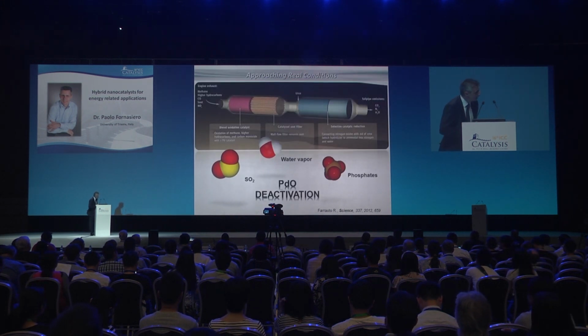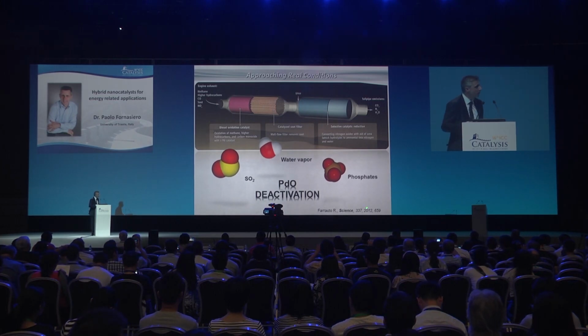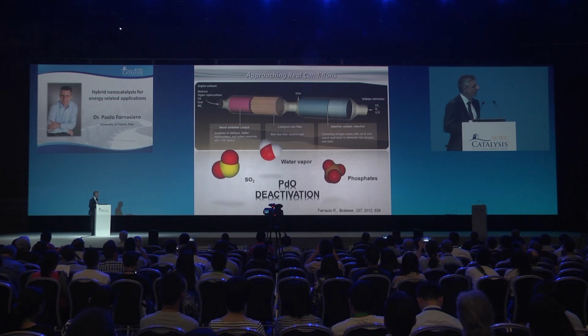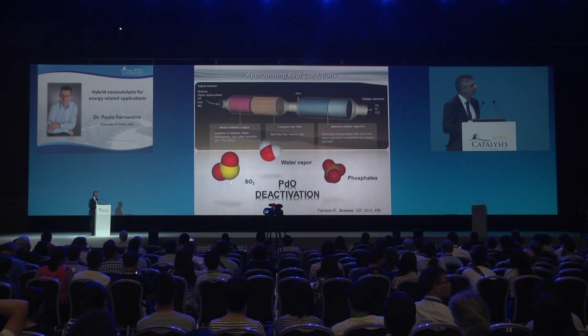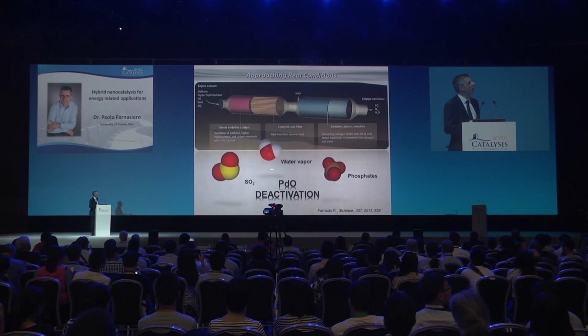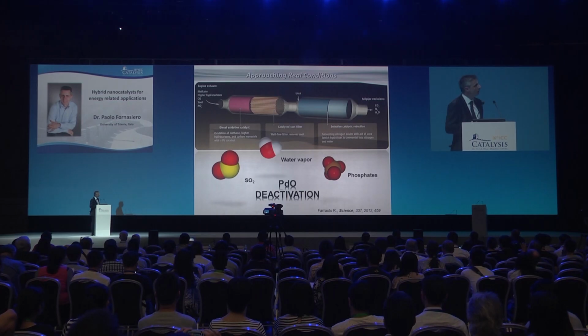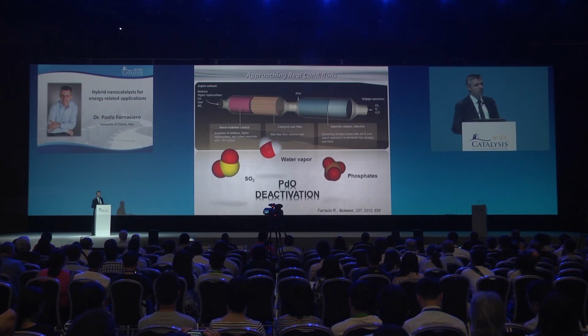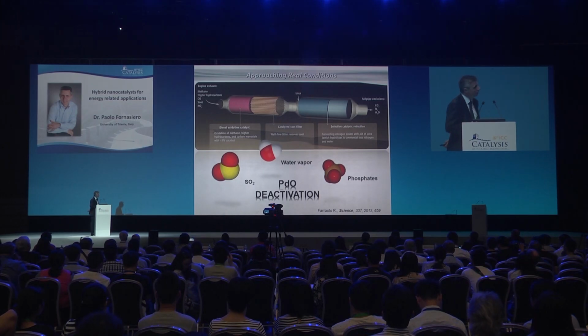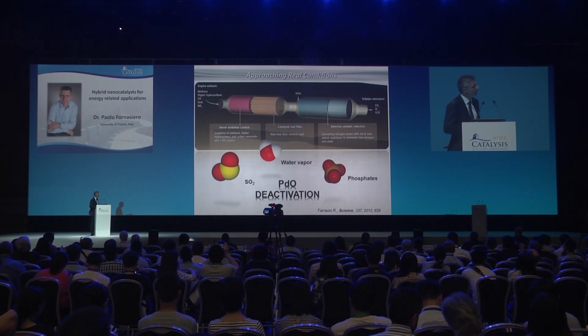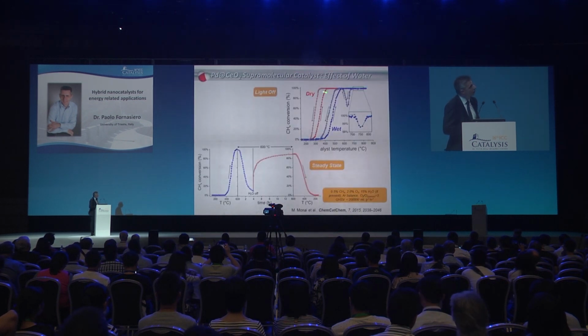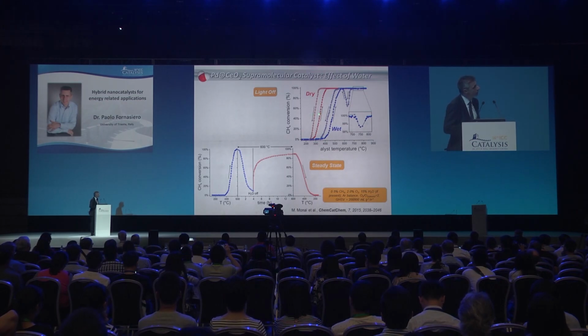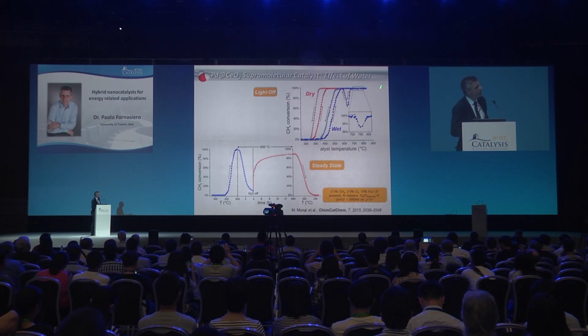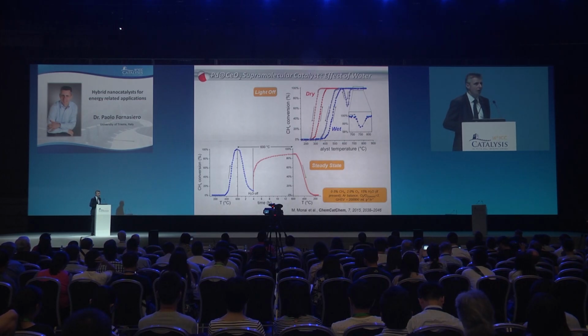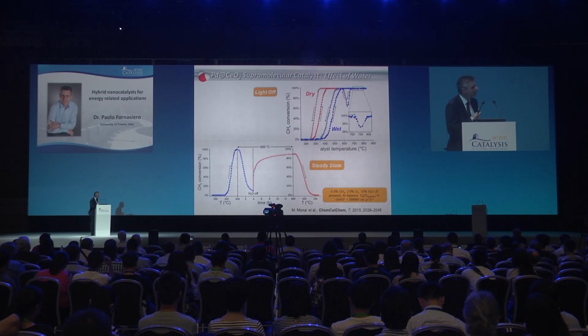Of course, those are very stable under dry conditions, but as nicely pointed out by Bob Farrauto in his comment to our article in Science, we also have to take into account real situations in which you have water vapor, phosphates from lubricants, SO2, which are expected to deactivate the catalyst. So we did a lot of investigation on the effect of these nasty components. For instance, the effect of water is quite dramatic. You can observe a shift in the light-off temperature from low temperature to medium temperature, still interesting for application. But in this case, we observed also deactivation at high temperature. So in some way, we are destabilizing the positive effect of ceria.